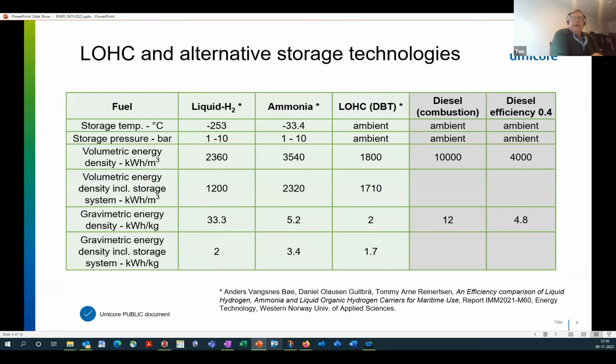So we have seen a couple of slides already on how the technology compares to alternatives. So I basically want to focus here on the volumetric energy density of the system. With a typical LOHC, we do better than with liquid hydrogen. We're not quite as high as ammonia. And if you compare to conventional fuels like diesel, we are at least a factor 2 to 3 lower, and that also goes for ammonia.